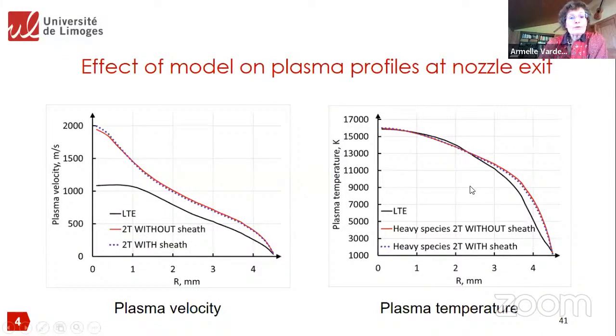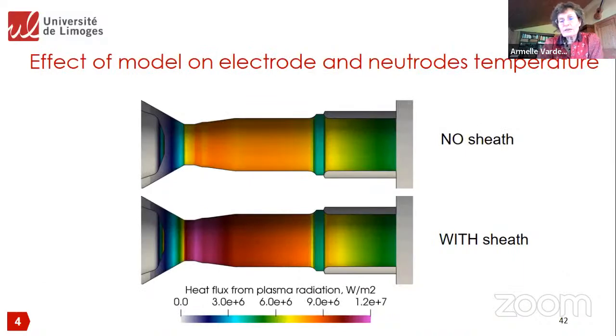Okay. Now, if you look at the profile you get at the nozzle exit, here for velocity and here for temperature, what you can see is that LTE gives really not so good prediction for the velocity. At least we assume that they are not so good, for the velocity. But for the plasma temperature, there are not so many differences in the prediction at the nozzle exit if we have LTE, two-temperature, and two-temperature with and without sheath. So depending on what you get, because you can use the profile you have predicted from this model for a model of material processing in the plasma jet. At the nozzle exit, perhaps the effect of including the sheath in the model is not so important.